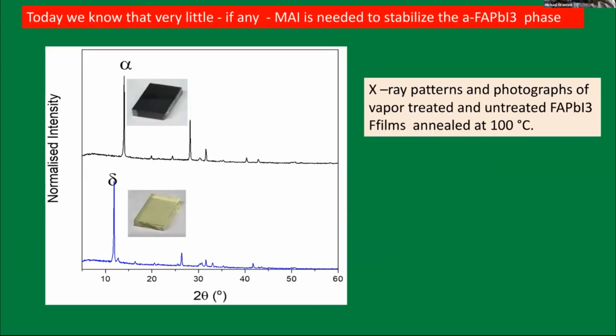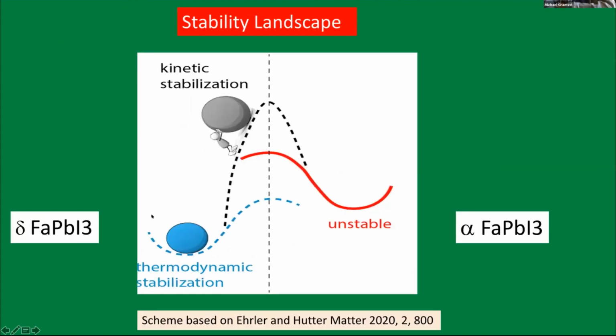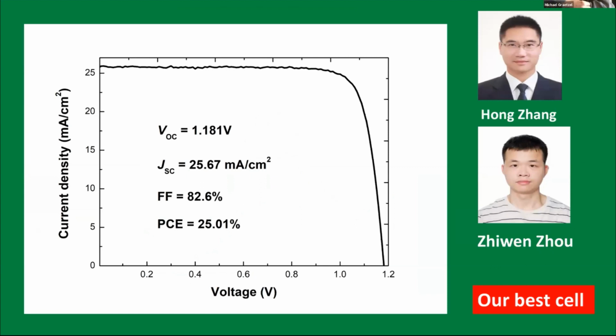Okay, so today we can make the black phase even at 100 degrees. That's 50 degrees below the phase transition temperature. So that's a heating with our new procedure, and this is heating without the procedure, the old procedure. And there's nothing magic about it. It's just that you stabilize. You have some kind of metastable system, because the alpha phase has a thermodynamic transition temperature of 157 degrees. And so if you're below that, you are by definition thermodynamically unstable. But what if you have a metastable state that can last for 100 years? Then you're okay for photovoltaics. Okay, so here's our best cell. And that brings me to the end.